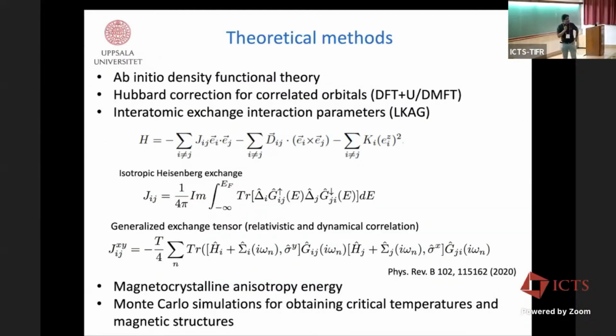So basically, the theoretical methods that I'm going to use today, the heart of everything is density functional theory. And I already told you about the electron correlations. Either we use, in some cases, DFT plus U in a static mean field way, or we use dynamical correlation in the flavor of dynamical mean field theory. The interatomic exchange interaction parameters are calculated with this formula, LKAG. These are the names of 4 authors. In 1987, they wrote down this formula many years back, and based on a Heisenberg model.